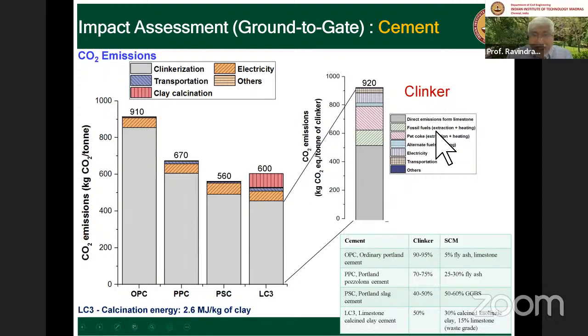Most of it comes from the gray part. The gray part is direct emissions from limestone. Okay, and then you have some part which is coming from the fossil fuels, pet coke, and so on. So all this is coming from the fuel. So this gray part in this larger diagram is the clinker part. Okay, and you see that as we decrease clinker, the CO2 emissions come down, as is obvious. I have here PPC, slag cement, and LC3. And you find that LC3 shows about 300 kg reduction in the CO2 per ton of cement. It is slightly higher than PSC in this case, but slag is not always available everywhere. So a better comparison is directly with OPC or even PPC. Okay, so you see that it comes out better.